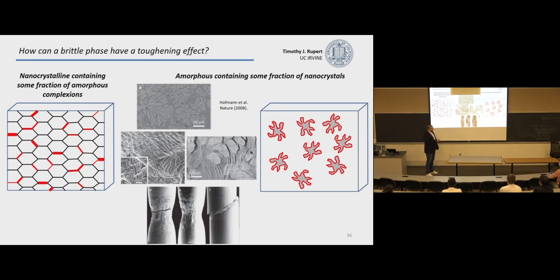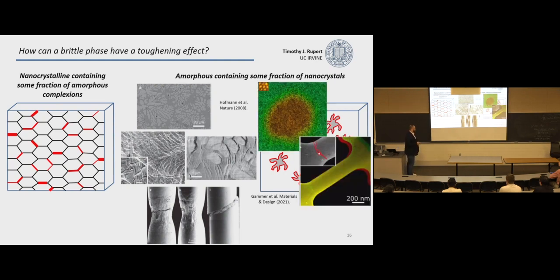The point here is that in this case, one shear band goes across the whole sample. When you add in all these nanocrystals, you get a bunch of tiny shear bands. So we're not changing that dislocations are moving around and being absorbed. We're just making it more tolerant to absorb those dislocations.